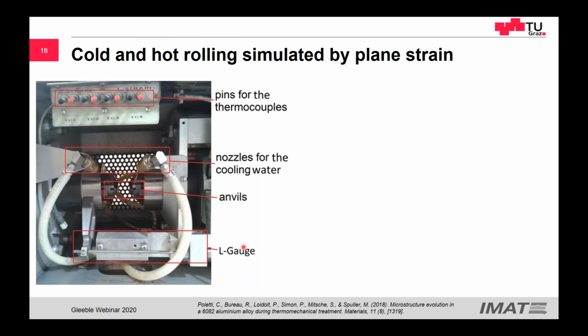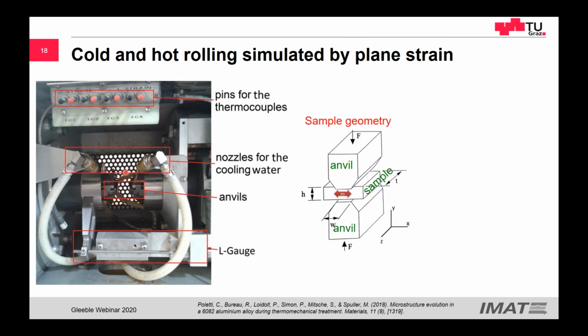So we have used the classical compression test with cylindrical samples, but also the plane strain. At plane strain, we can better simulate the conditions during hot rolling. And the most interesting part for us, I hope the people from Gleeble will not be mad at me, is the in-situ cooling. We love it. In-situ cooling for aluminium alloys is really very important, and I will show you why.